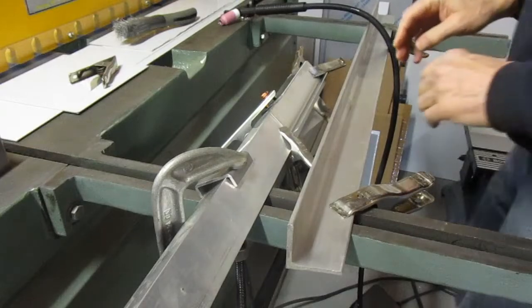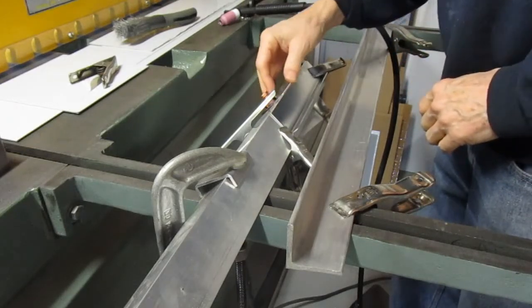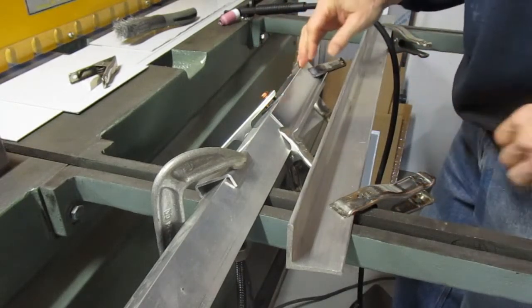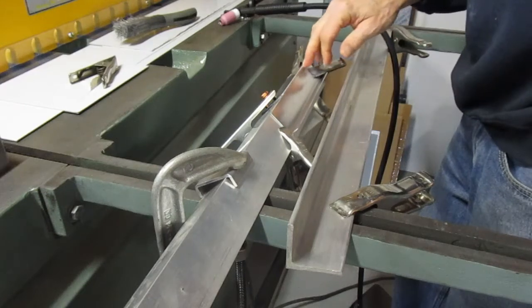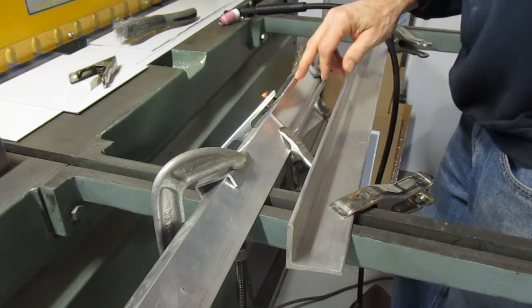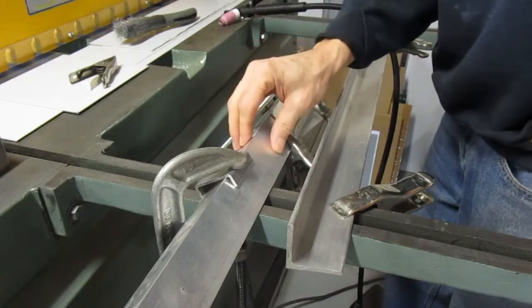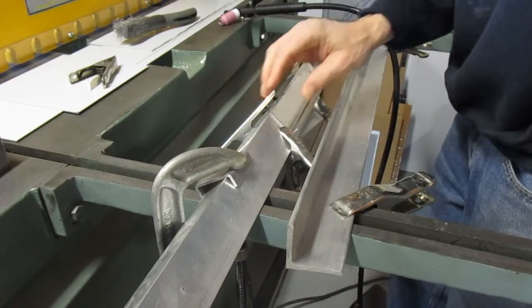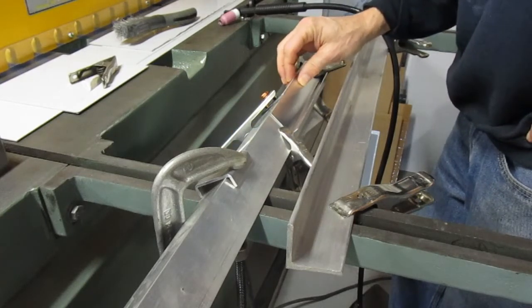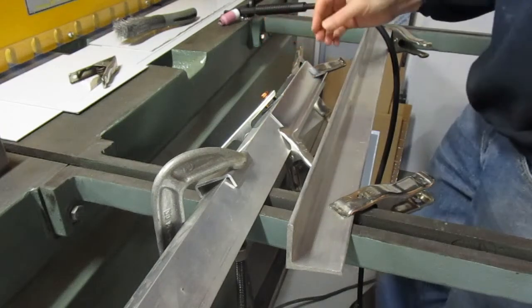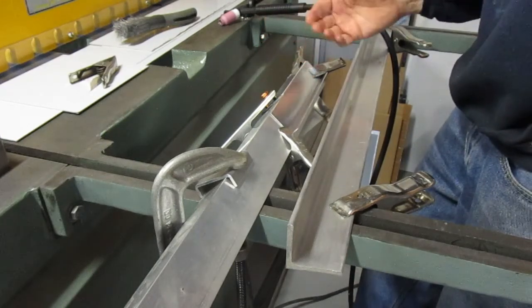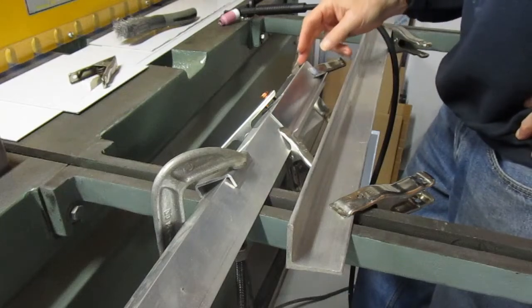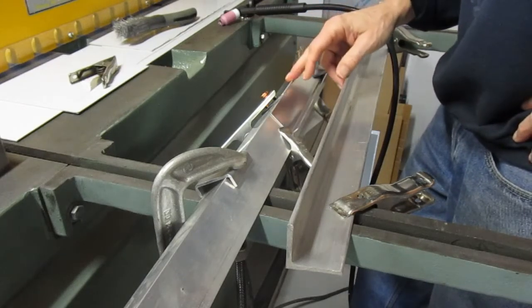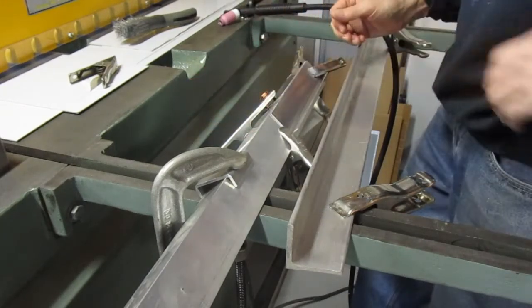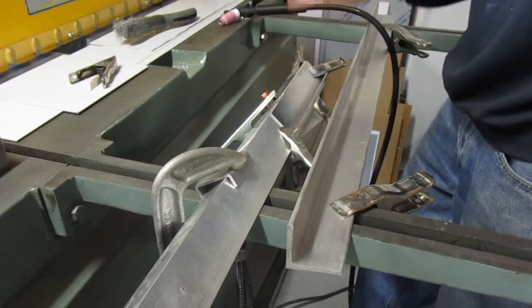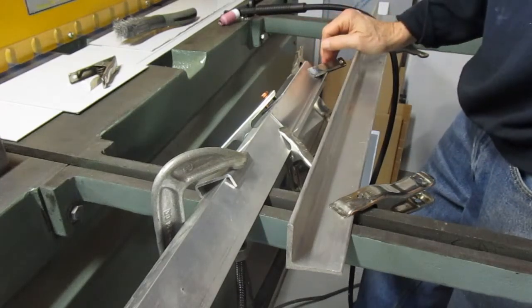Here's my welding setup. I put in 2 pieces of scrap metal, 16th inch aluminum, and I simulated the open corner along here. Basically what I have is a right angle piece of extruded aluminum to hold this in proper form. It also takes the heat out of the metal because aluminum has a very watery puddle, and if you don't back it up with a heat sink, the metal just flows away and the corner opens up and you can't fill it, and it just turns into a mess.